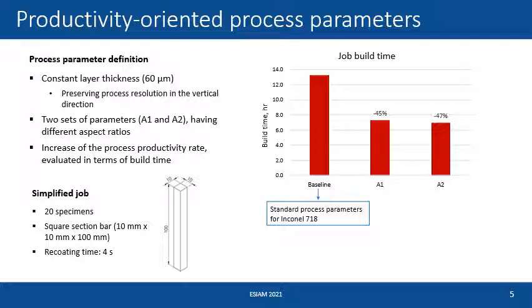If we compare the job build time between the standard process parameters for Inconel 718, here named baseline, also in the further slides, and the selected process parameters, we see that the selected process parameters introduce a strong job build time reduction, which is almost halved, both for the two possibilities of process parameters that here are investigated.